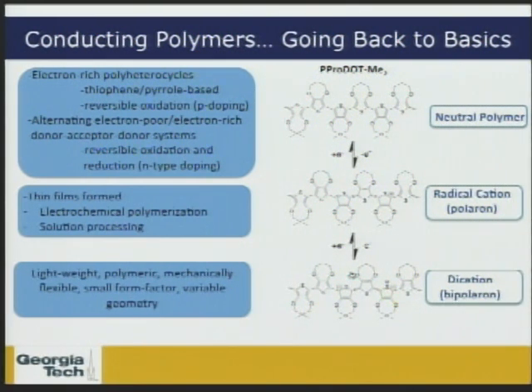So, conducting polymers, conjugated polymers, you go back to basics, and a system that we've worked on for a number of years is based on dioxythiophene type systems. Specifically, these are propylene dioxythiophene systems that seem to have lost some methyl groups here, but we'll ignore that right now. The general idea being that the neutral polymer can be created as a film. The film can be prepared by either electrochemical polymerization, if you're looking at small electrode-adhered materials, or by solution processing, and I'll talk quite a bit about that as I go along today.